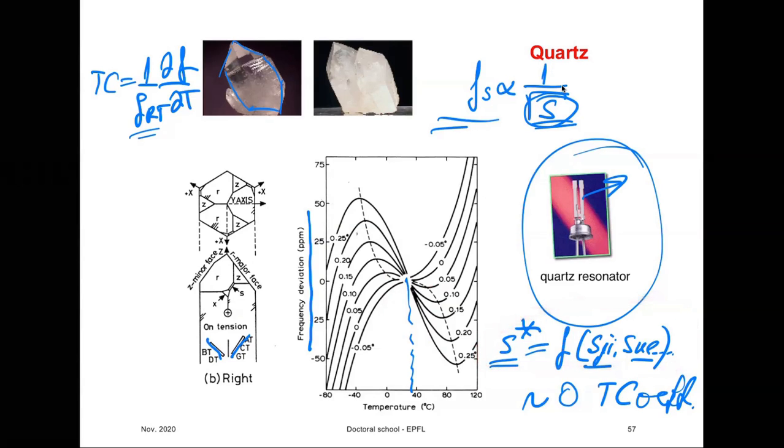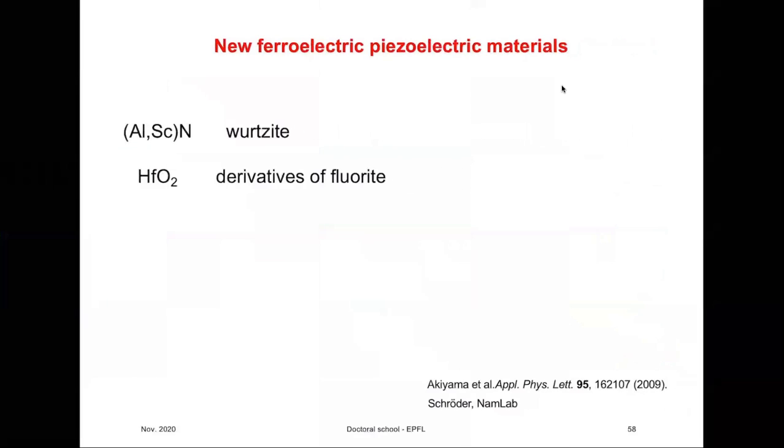If you know crystallographic values of, let's say, elastic compliance along a crystallographic axis, then you can calculate what would be the value along an arbitrary direction. And if you know the temperature dependence along a crystallographic axis, that will also give you the temperature dependence along an arbitrary direction. So you don't have to measure every time. It's enough to determine this along principal directions, and then with the Euler transformations, you can get it in other directions.